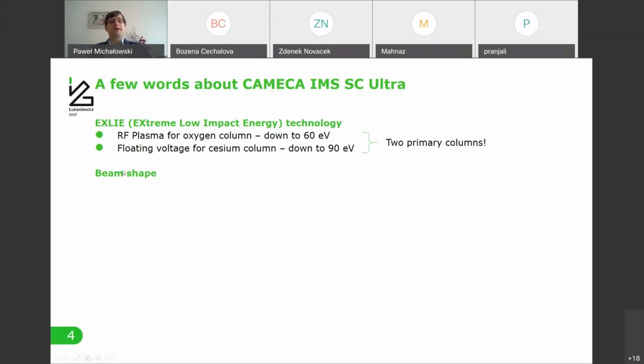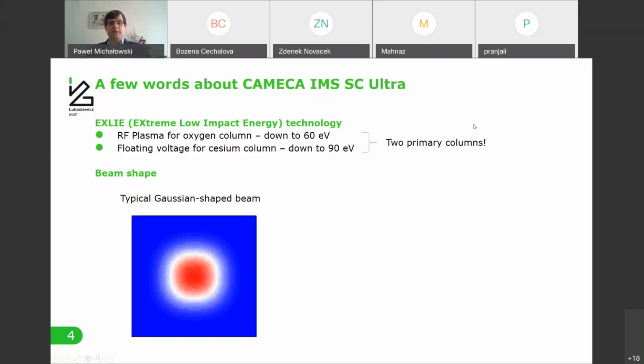It is the case of the beam shape, because typically when you generate the beam, it is a Gaussian-shaped beam, so the center of it is usually more intense than the edges. So if you think how such a beam is sputtering the material, it's quite obvious that the middle part will sputter it a little bit faster than the edges. So the difference can be like 2-3 nanometers. And then obviously for such a difference, when we want to consider two-dimensional materials like graphene, which is well below 1 nanometer, it's not good enough. This will blur our signals quite significantly.